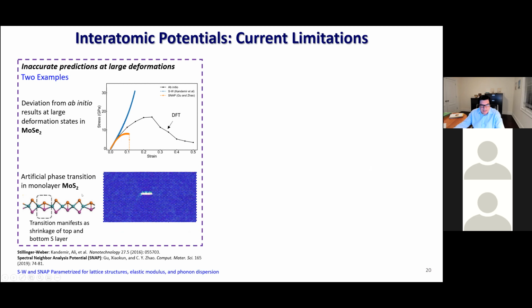But when you put this configuration in molecular dynamics with DFT force fields, so ab initio molecular dynamics, it's not stable. So it goes back to the original configuration. That tells you that this most likely is an artifact of the force field. So this left us with no other alternative than to start looking at how to improve this force field, because in a fracture problem, you have many atoms, the size of the domain is important.